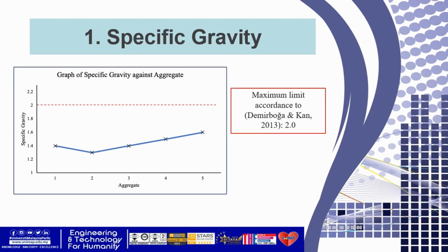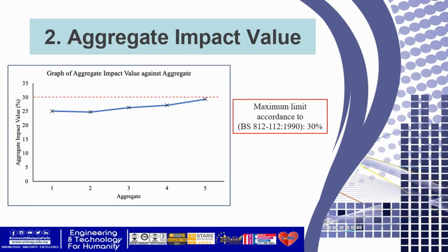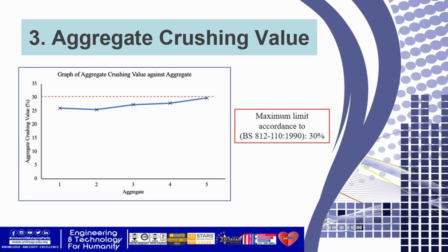For the specific gravity, as you can see here, all samples show a specific gravity less than 2.0, which can be considered as lightweight aggregates. And the aggregate impact value for all samples is less than 30%, which shows that the aggregate produced is a strong aggregate. The same pattern also shows for the aggregate crushing value. The results are below 30%, which can be considered as a strong aggregate.